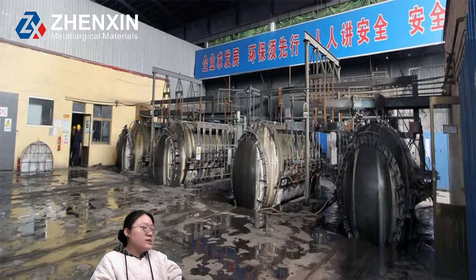Important point here, the effective magnesium content in iron is very low. Normally only 0.03 to 0.05% magnesium remains dissolved, but that tiny amount controls everything. That's why nodulizer quality and magnesium recovery rate matter much more than people think.